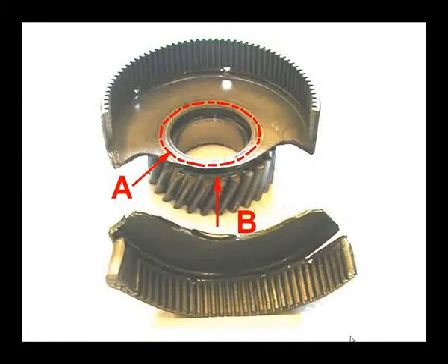However, after approximately 2,000 hours of use, many of these components did fail in the field. Upon review of several failed gears, it was apparent that something else was happening in the system beyond simple torque. Had the part failed due to balanced torque, the failure would have followed the perimeter of the weld. This crack did initiate at the weld, as shown by point B in the image, but followed a symmetric path out to the perimeter of the drive ring that is inconsistent with torsional failure. All the failed parts showed the same crack.